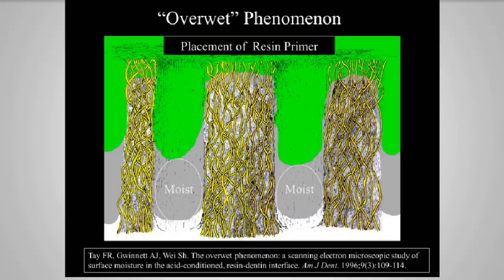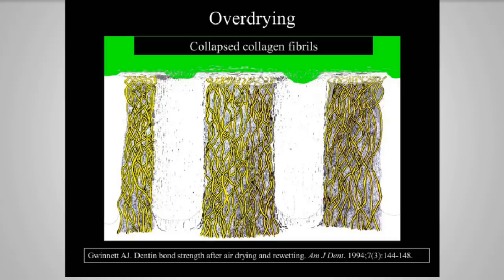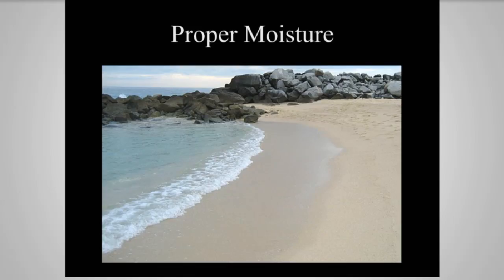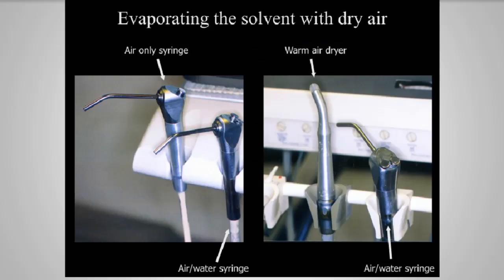Now the challenge with this particular system, that is with the total etch technique, is if the dentin is too wet or too moist, the moisture prevents the resin from going into the dental tubules, and we get the formation of water trees. If it's over dried, the problem is that these collagen fibers can collapse, and we decrease the bond strengths from the formation of the hybrid layer. So what we're always looking for is that elusive, proper moisture. So this is obviously here too wet, and this is too dry, and of course right here is what we're looking for in the middle. That's very hard to define, and it may even be different from bonding agent to bonding agent.